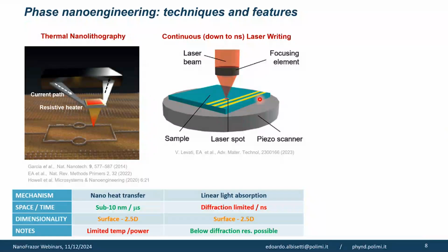So we're now building a system that uses nanosecond lasers. Usually the shorter the pulse, the more confined the heat generated can be. So usually going to short times is a little bit better for spatial resolution. So it's good to try to go towards nanosecond lasers.